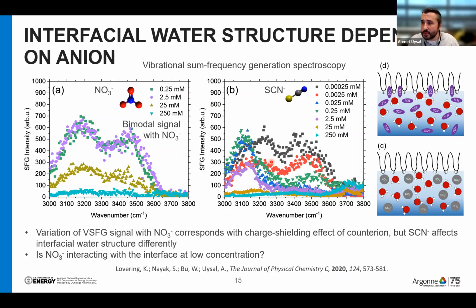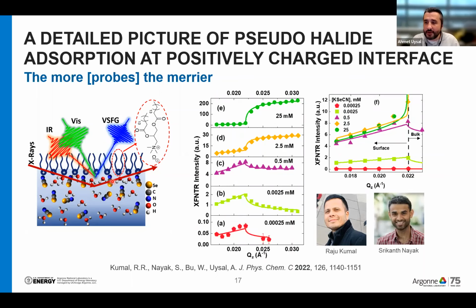To do that, instead of thiocyanate, we introduced selenocyanate, because selenium has a very nice X-ray absorption edge. It is very similar to thiocyanate in its behavior. So we can use X-ray fluorescence to understand the ion adsorption at the interface, and also use all the other probes that we have been using. Especially with the SFG, we can also look at the CN stretch, and now we can compare what we see with X-rays and what we see with SFG, and it will give us a better understanding of the behavior at the interface.